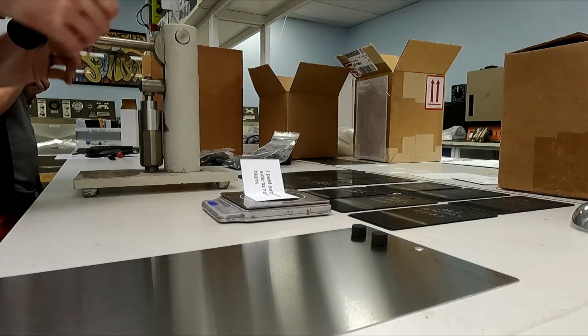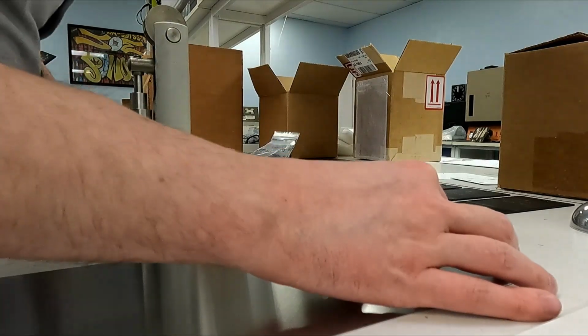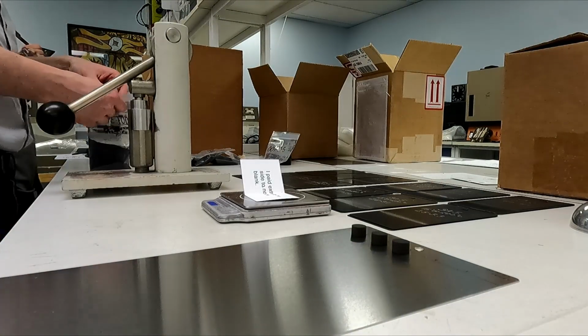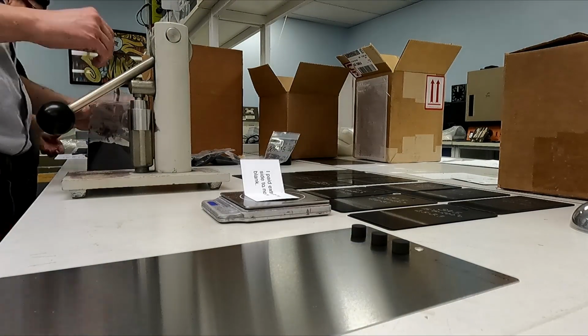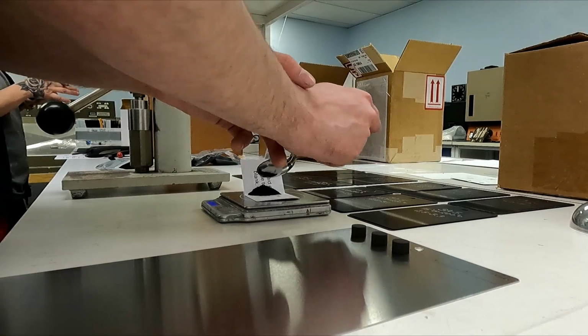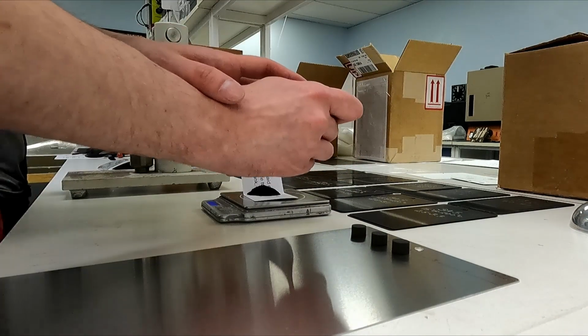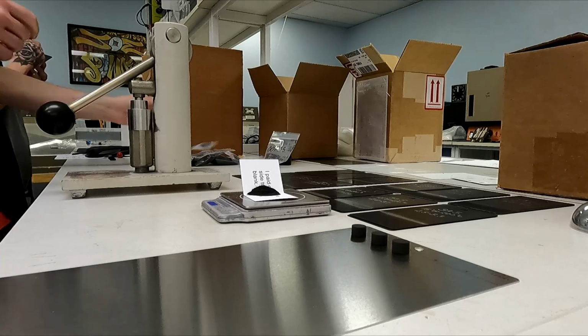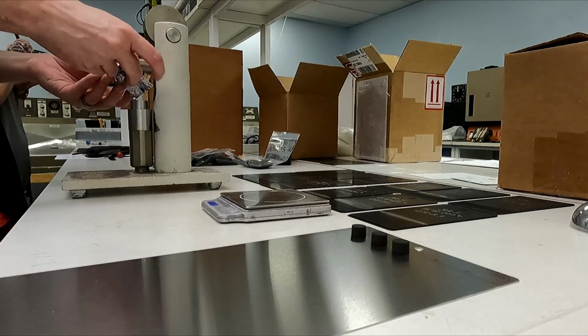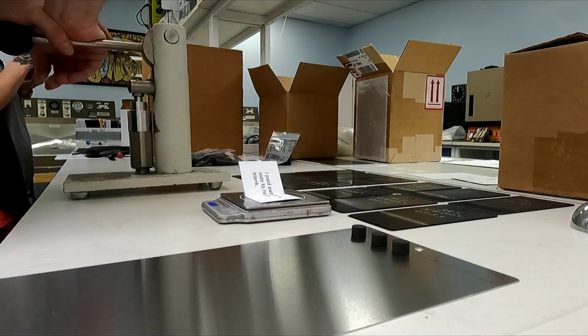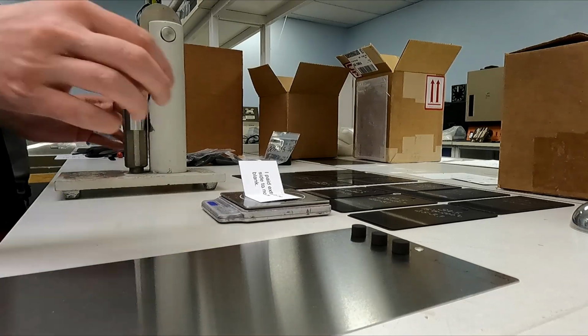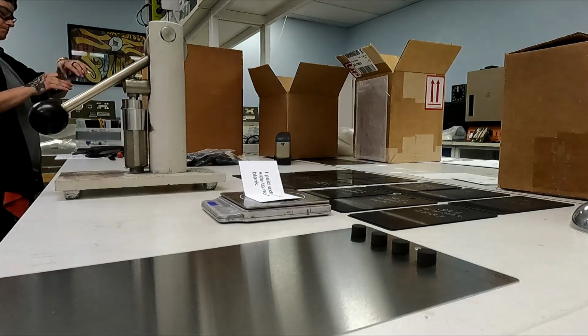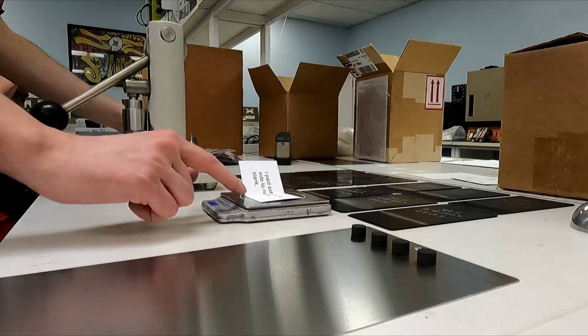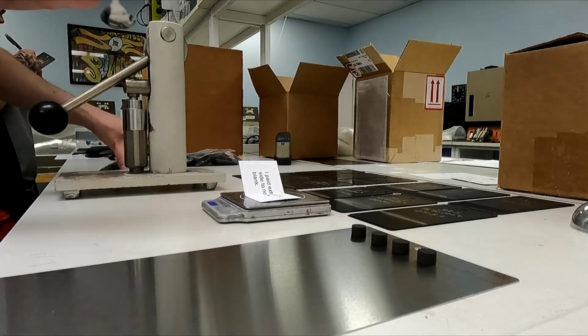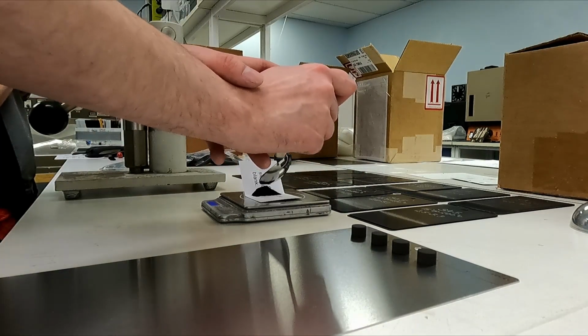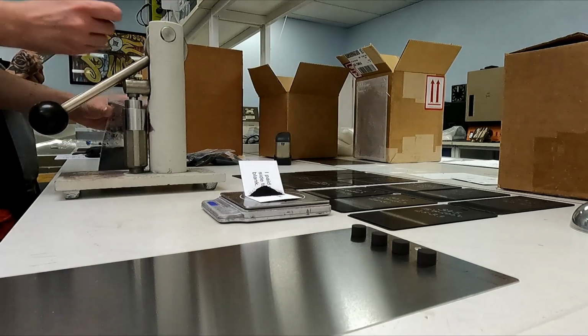The pellet is affixed to a glass or smooth steel plate through heating the plate such that the underside of the pellet only just begins to melt and adhere to the plate. At this point, the plate is attached to a holder that allows it to stand at 65 degrees from horizontal, and the whole assembly is then placed into an oven at the cure temperature of the coating for long enough to fully cure the powder. As the pellets heat in the oven, they will begin to melt and subsequently flow down the inclined plane as the mass of powder begins to behave as a viscous liquid.